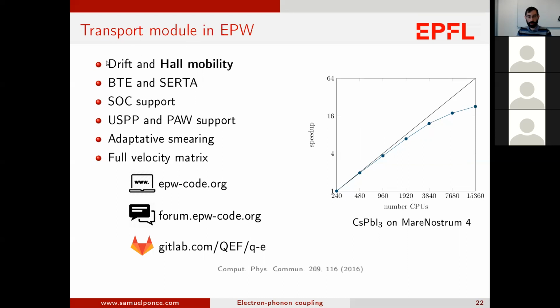I've shown the equation for drift mobility, but actually in practice, most experiments are Hall mobility experiments. In those experiments, what is done is that they apply an orthogonal magnetic field to the sample, orthogonal to the current flowing, and this will deflect the carrier through the Lorentz force. It will deflect the carrier to one side of the sample, and then they measure the change of potential. But of course, this additional magnetic field will be an additional driving term in the Boltzmann transport equation. And so now we also have implemented that in EPW. And so it's also possible to compute the Hall mobility and the Hall factor, so also including the effect of external magnetic field on the motion of charge carriers.